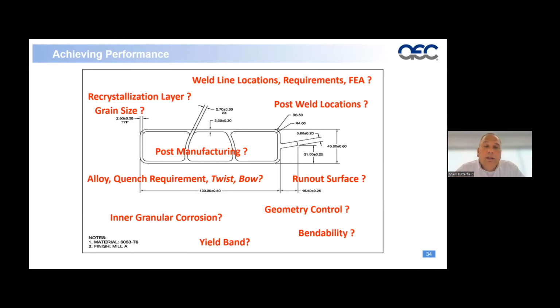Post-manufacturing, alloy, the quench requirement, twist and bow. That's where we need to really understand what the post-manufacturing is, what type of assembly is going to occur, is welding going to take place? Therefore, we can start to understand what twist and bow would be acceptable. We can reverse that back into a quench that's going to be required, and that will help drive the alloy. Runout, surface, geometry, yield bands, intergranular corrosion. These are things we want to take advantage of understanding during this phase of the design. Because a lot of these can be changes made that have no impact to cost, but have a significant positive impact on the performance of the product, and help mitigate downstream risk relative to post-manufacturing or post-extrusion processes.